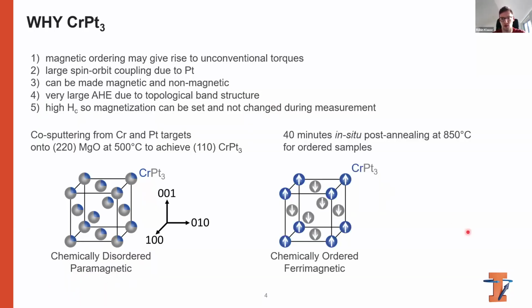When we add a 40-minute in situ post-annealing step at 850 degrees Celsius, we get chemically ordered samples, where the chromium atoms always occupy the corners of the cubic cell, and the platinum atoms always occupy the face-centered sides. In the chemically ordered phase, the chromium-platinum-3 is ferrimagnetic. But note that the crystal structure is still the same between chemically disordered and ordered - they're still both FCC crystals. Only the chemical ordering and the magnetism is different.